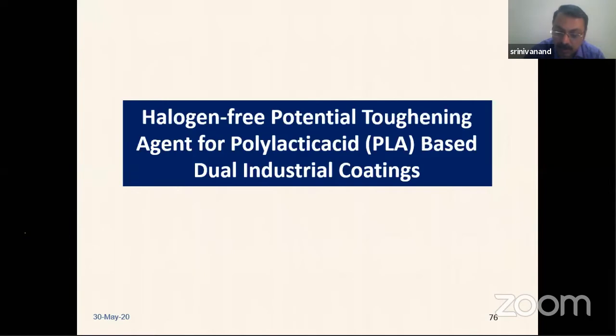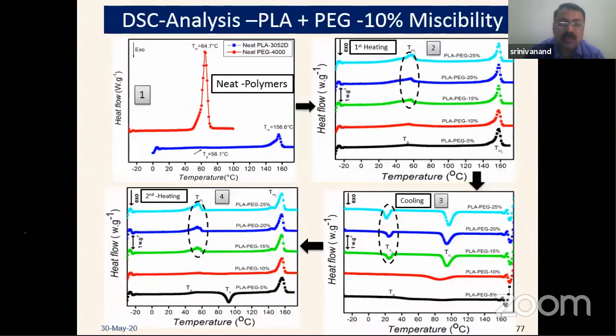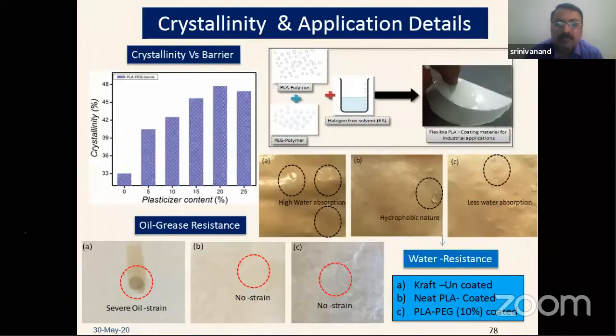non-halogenated solvent incorporated PLA systems, and then we did the DSC studies, because the time is almost done, I guess. So we could understand that PLA having 10% of PEG is able to form an excellent film. Beyond 10% of PEG, it forms phase separation, and accordingly we get a different melting point. That melting point corresponds to the melting point of PEG.